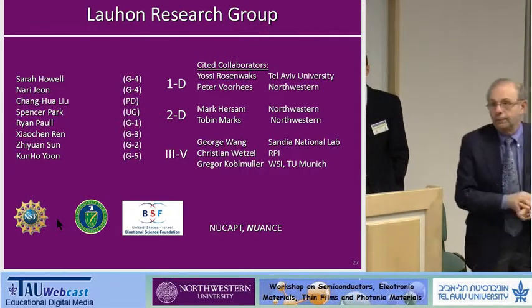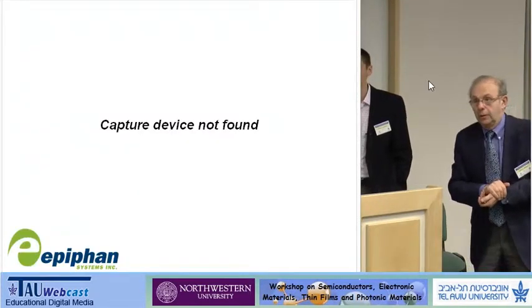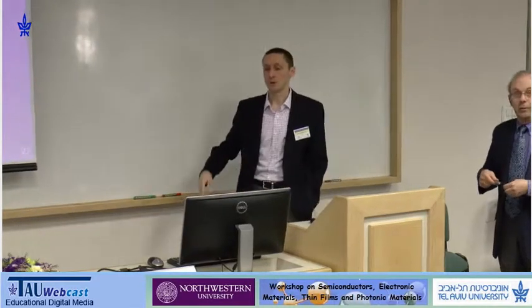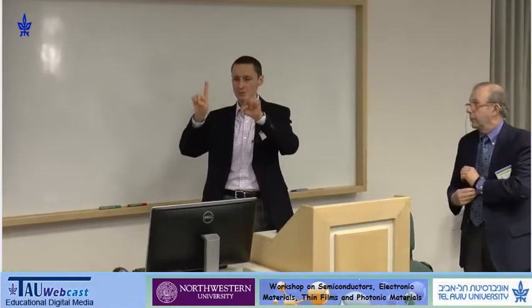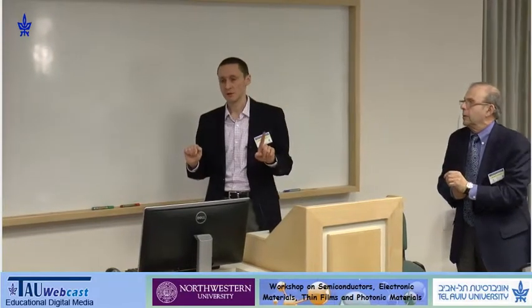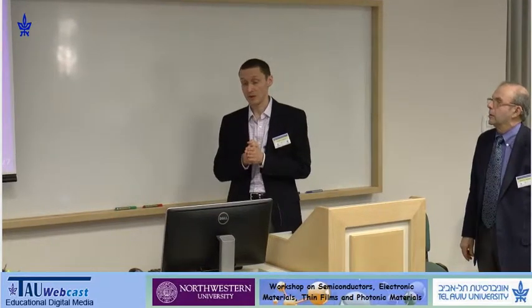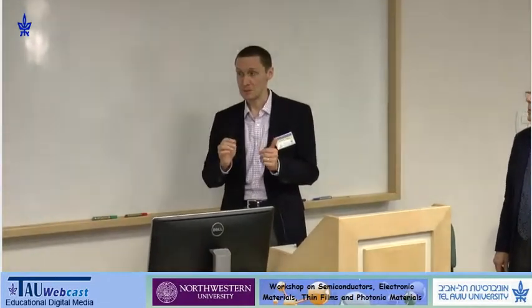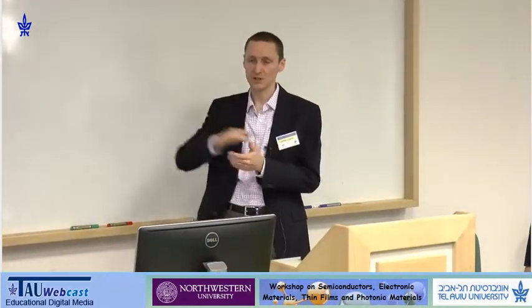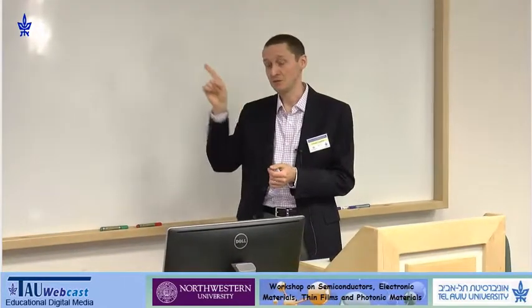Questions, please? Yossi? I didn't understand what's the role of the grain boundary in the memory effect? So the grain boundary is resistive. So if you have a grain boundary that bisects two electrodes, you see a potential drop there. Okay? But the grain boundary is also correlated with a distribution, we think, of sulfur vacancies, which are conductive. So it's not simple to explain, but we've looked at how bridging between electrodes, bisecting, and then this other geometry of intersecting grain boundaries influences the electrical characteristics.